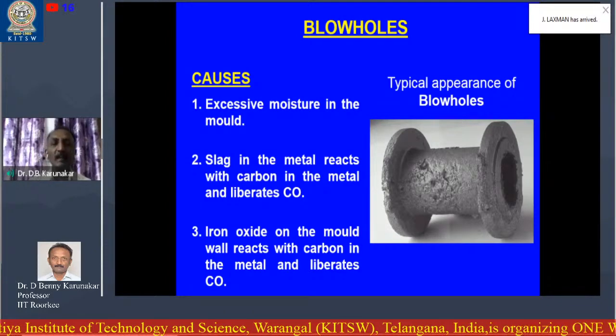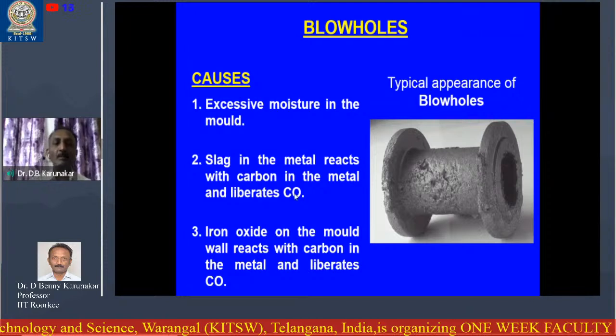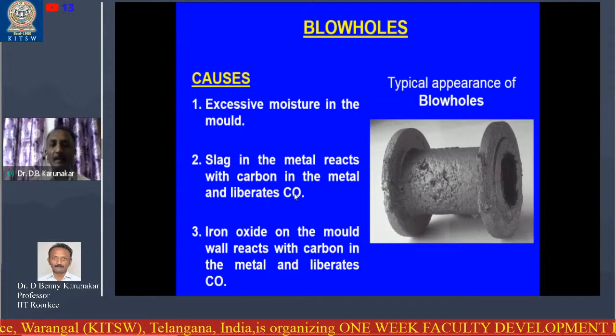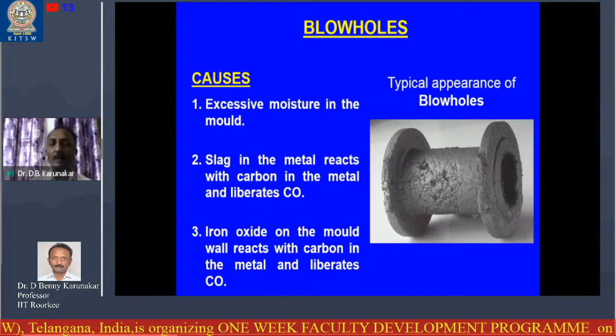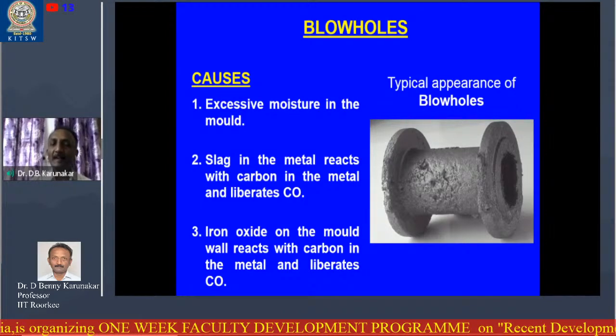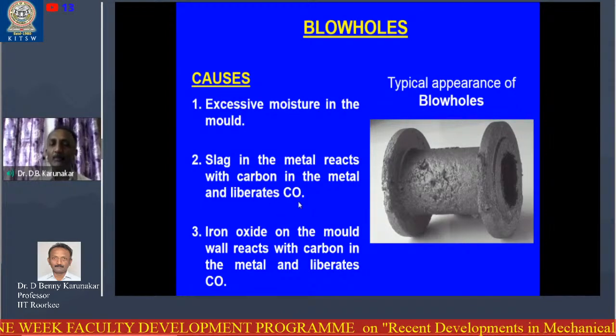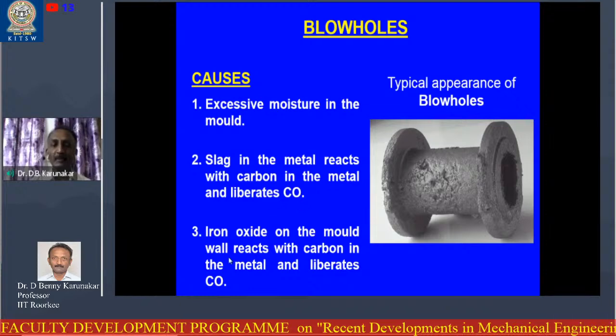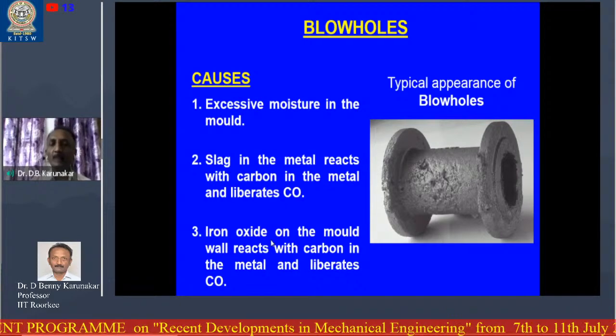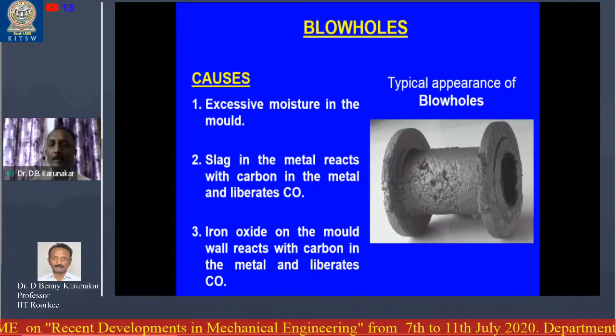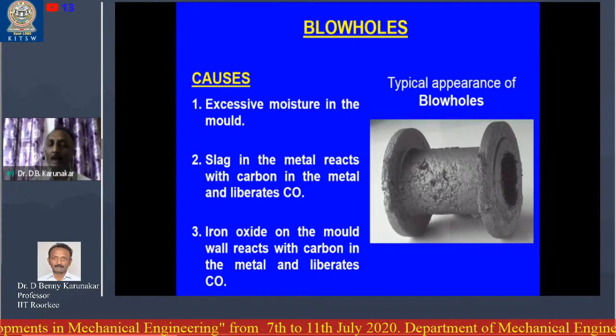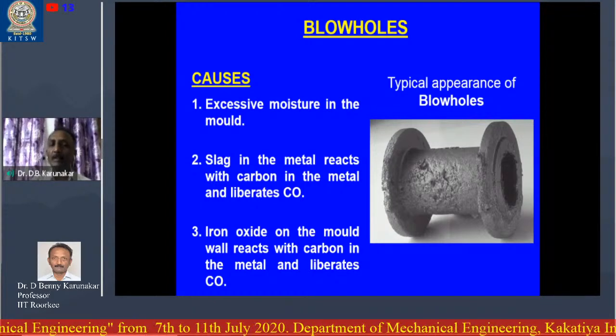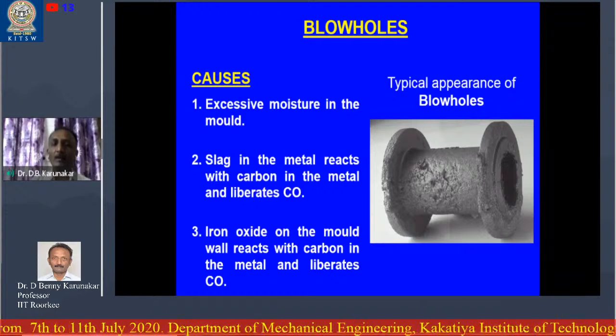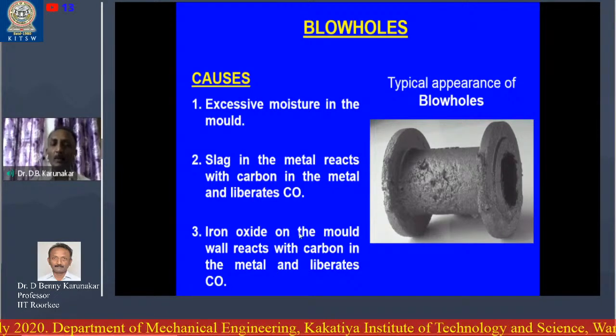Similarly, the slag in the molten metal - what is this slag? The slag contains silicon dioxide that reacts with the carbon and forms carbon monoxide. Same is the case with the iron oxide, FeO. From there, oxygen reacts with the carbon in the molten metal and forms carbon monoxide.